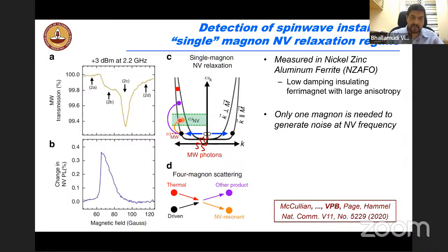And that's why the NV frequency shifts away. Again, I should point out that if everything is uniform, if it's zero K, a uniform magnetization will not create a magnetic field at its center. So what you need is some fluctuating magnetic fields, and that's why we need these non-zero K magnons. And those are what can couple to the NV centers, and that are what is being created here.